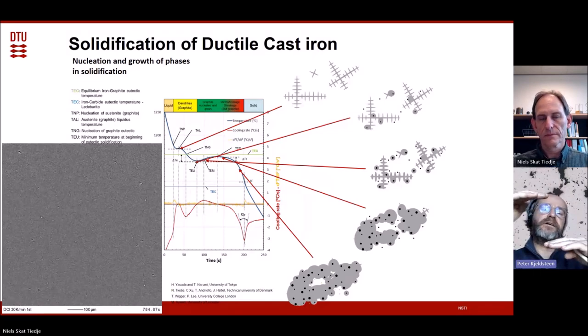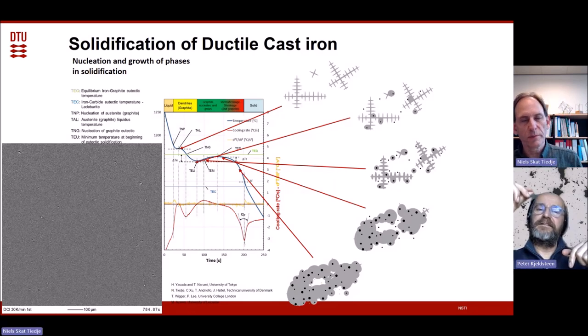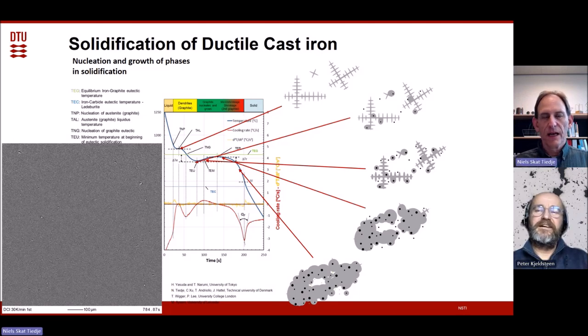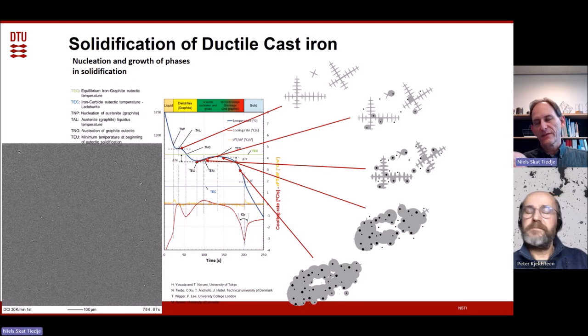You can control that by adding nucleation powder. Exactly, it's a big business. Actually, I add magnesium to make sure the graphite becomes nodular, spherical. So that's the first part. Then, what are your nucleation sites? Then you add what are called inoculants that contain aluminium, calcium, zirconium, barium, and lots of other things, tuned specifically to your use.